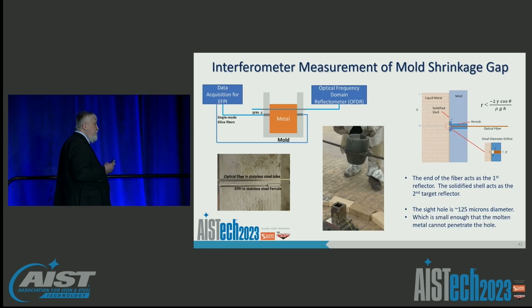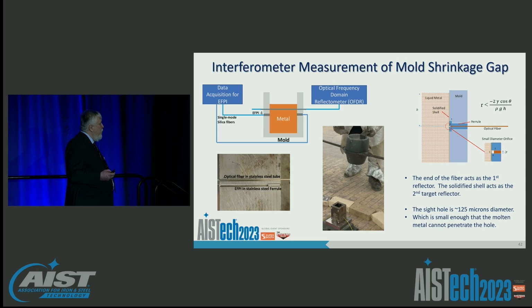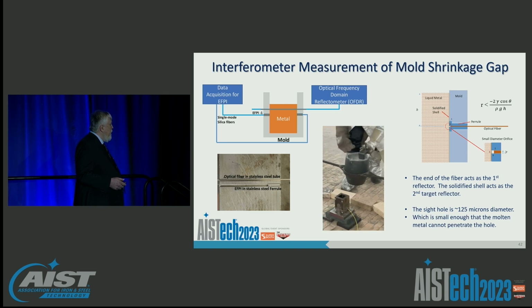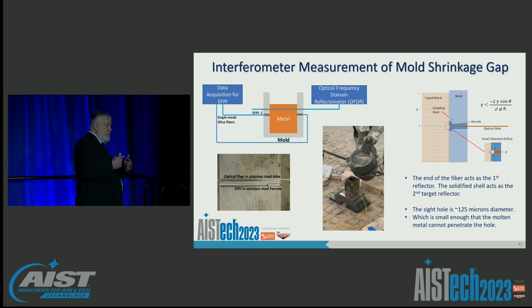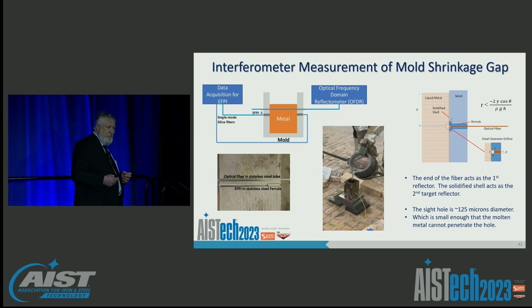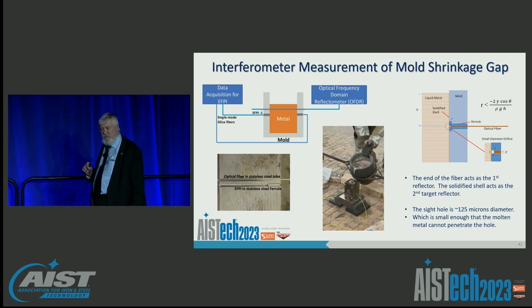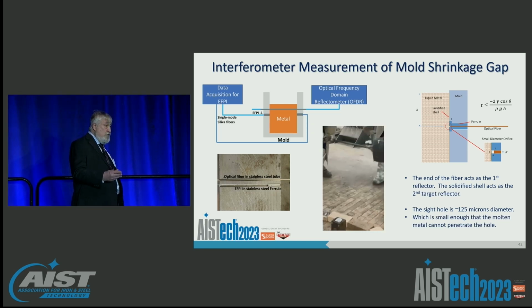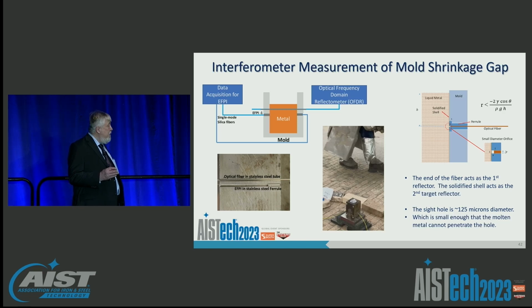And I also mentioned the interferometer technology. Interferometry, it turns out, can be quite useful for measuring things like solidification gap development in the casting process. This is an example of two interferometers placed into a static mold. In this case, the demonstration is with aluminum, but what we're able to show is that that sensor has direct line of sight into the mold cavity with a very small, about 125 micron sight hole. And the surface of that solidified steel or aluminum can actually serve as a reflector, and we can actually dynamically measure the gap during that process.